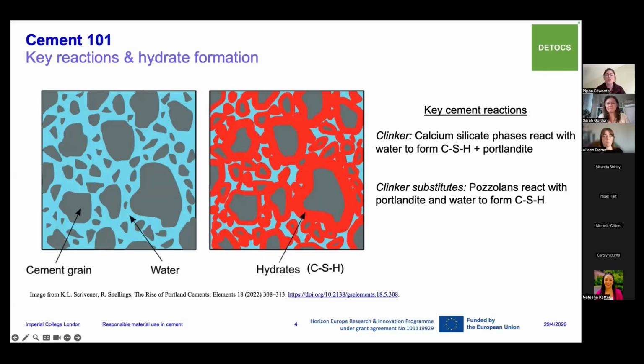concrete. So cement clinker contains reactive calcium silicate phases, which we've made at high temperature and they're pretty unstable, which dissolve quickly. And they precipitate the hydrates and another phase called Portlandite. Clinker substitute materials generally react more slowly and they consume Portlandite to produce hydrates, which means that they mainly contribute after the clinker has been reacted. And it also means that we can't fully displace clinker in cement. So overall, strength development comes from dissolution and precipitation reactions, with clinker dominating in the early stage and early strength development, and substitute materials contributing later.